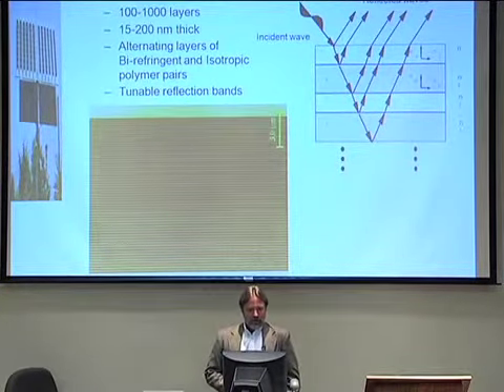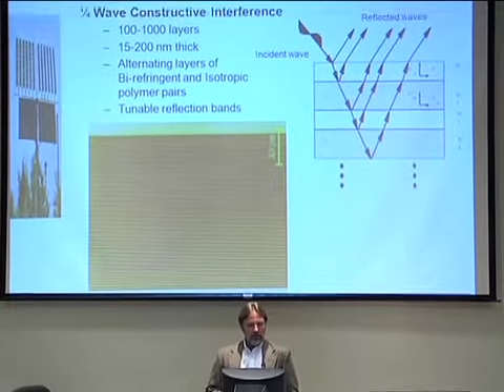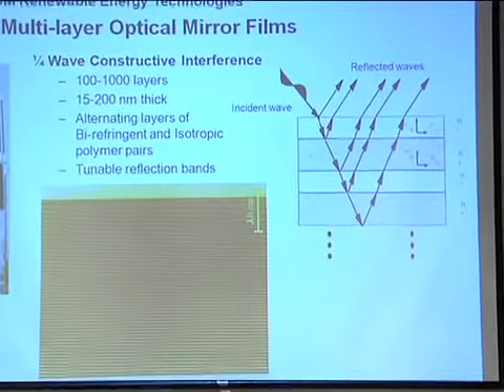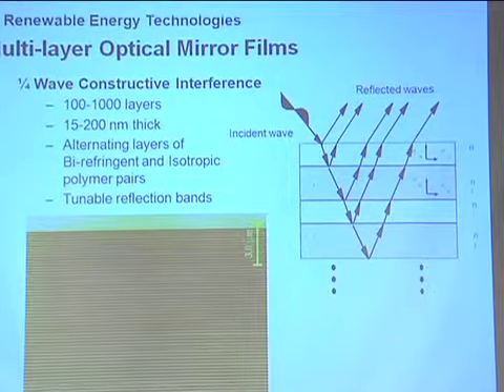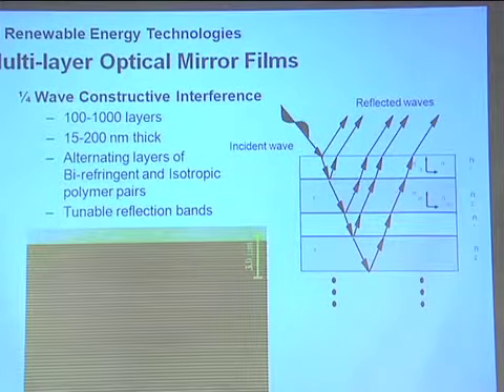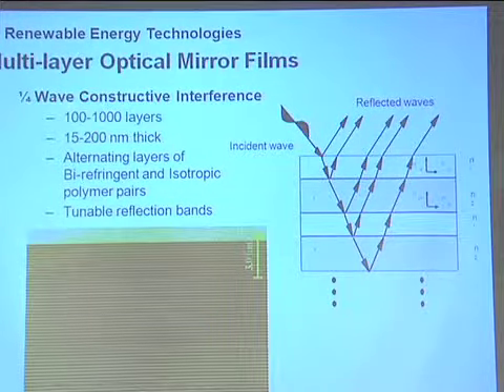So this is a technology that I've spent a lot of time on in the last 15 years. It's a very sophisticated technology where we make these quarter-wave constructive interference mirror films. They're comprised of hundreds of layers of alternating materials, where one material is a high refractive index polymer and the other one's a low refractive index polymer. And we bring them together in a manifold and make a film out of them.